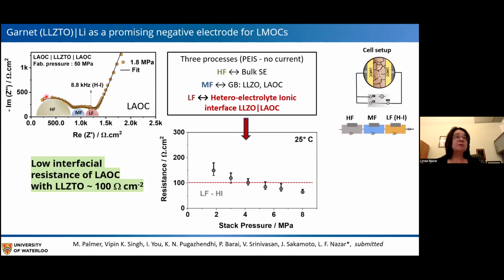This is a Nyquist plot showing the data for LAOC. We can identify three components, three processes in the impedance in the EIS. A high-frequency component, which is the bulk solid electrolyte, a medium-frequency component, which is the grain boundary between the garnet and the LAOC, and this low-frequency component, which is our hetero-electrolyte interface.